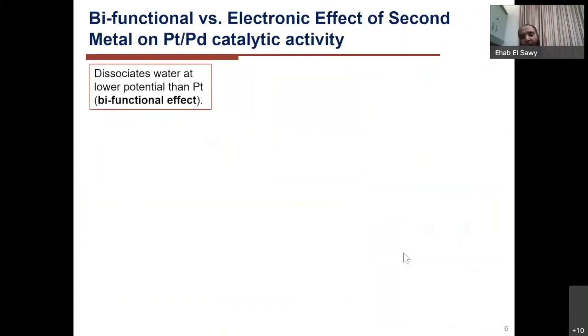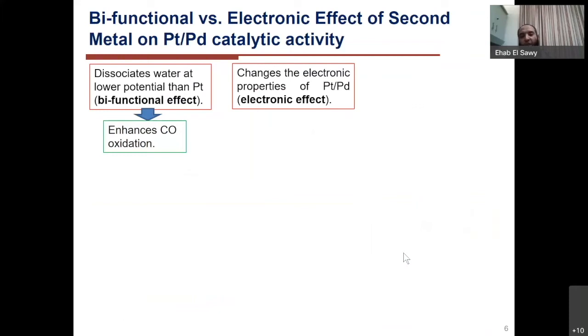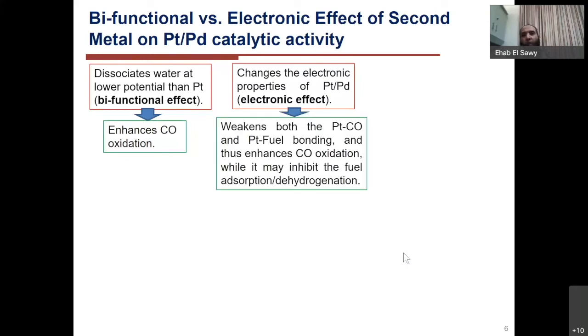So if the second metal has the ability to dissociate water at lower potential, in this case, that oxygenated group at the surface will help oxidize the carbon monoxide, and we say the second metal enhances the catalytic activity through the bifunctional effect. However, if the second metal is changing the platinum electronic properties, so it's modifying the adsorption ability of the catalyst, it's weakening the carbon monoxide adsorption. However, at the same time, it will also affect the adsorption of the fuel, and therefore it may also hinder the catalytic activity of the catalyst.